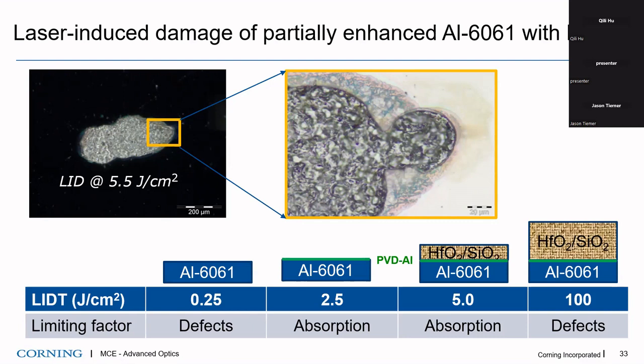What's the absorption mechanism at the defect? Is it usually exciting surface plasmons? What's causing the enhanced absorption that produces the damage when you have a defect? That's a good one. In a simple approach, a defect functions like an optical lens that makes the field more focused. Compared with a defect-free coating, a cone shape optically focuses the beam. If it's a collimated beam, it's focused all the way down to the substrate. That's one of the possibilities.